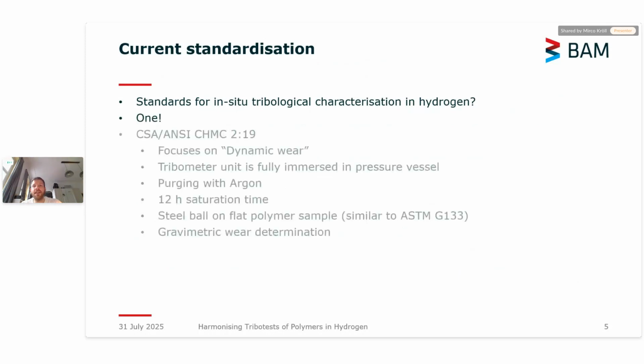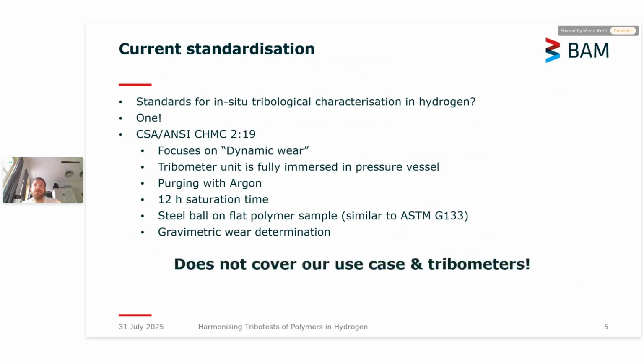And there's actually one. There's a Canadian American standard, which is actually a compendium of several things when you want to investigate the hydrogen influence of polymers. And one part of that standard is the dynamic wear. There's a tribometer unit described that is fully immersed in a pressure vessel. They're purged with argon prior to testing. They have a 12-hour saturation time, and they have a steel ball on flat polymer sample setup. And they determine wear by weighing the samples before and after the test. And we are asking ourselves, well, is that covering our use case in tribometers? And we had to say, no, it does not.